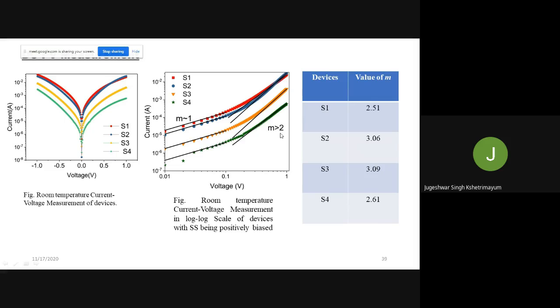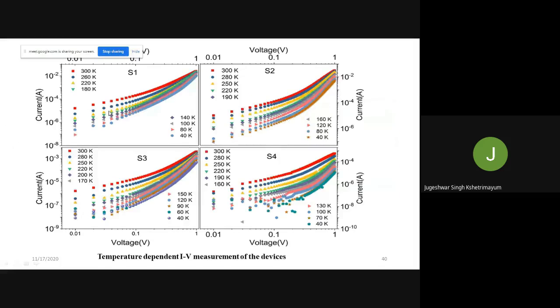Okay, so now here we are analyzing the IV characteristics for some temperatures. We go down to 40 Kelvin. Generally, we have the data up to 420 Kelvin, but we are not showing it because of the low temperature measurement. So we do it for some selected temperatures. We start from 40 Kelvin to 300 Kelvin. We have more, but we are showing this, the I versus V characteristics for S1, S2, S3, and S4.